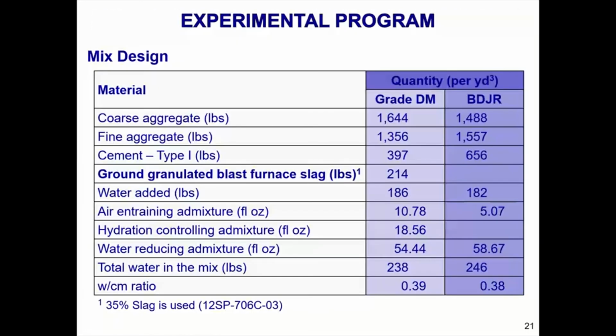We also looked at 2 MDOT bridge deck mixes. We looked at our grade DM and we looked at our grade BDJR. The grade DM, you can see, substitutes some of the type 1 cement with ground granulated blast furnace slag. So we have 2 different mixes.